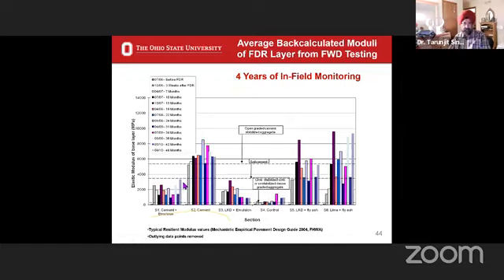And so what we find is that, and I have drawn certain lines here, this is the elastic modulus of lime stabilized soils. Here is soil cement, and this is where the line is for open graded cement stabilized aggregate. And if you look, the cement one did well, and there isn't as much variation in the cement one as you see in the LKD fly ash and lime and fly ash. They also worked well, but slightly less. You see much more variation here. There isn't much variation with time, right? Here, there's a lot more variation that happens with time.